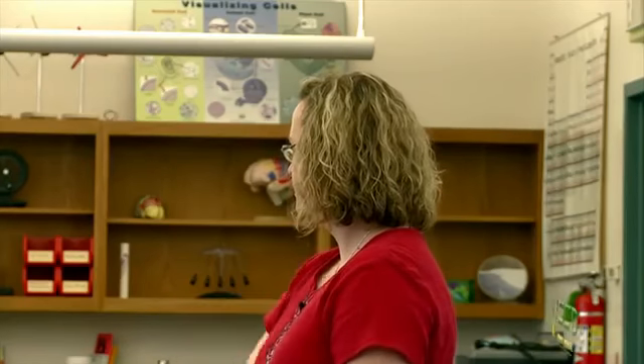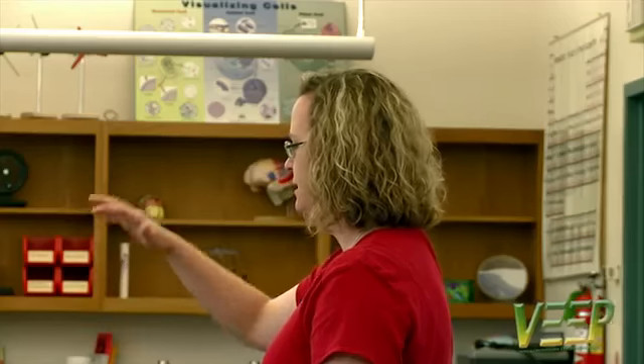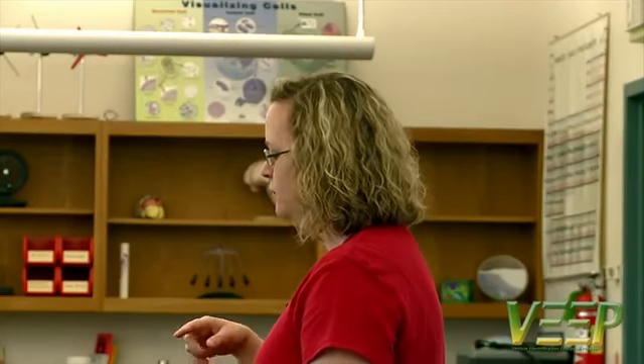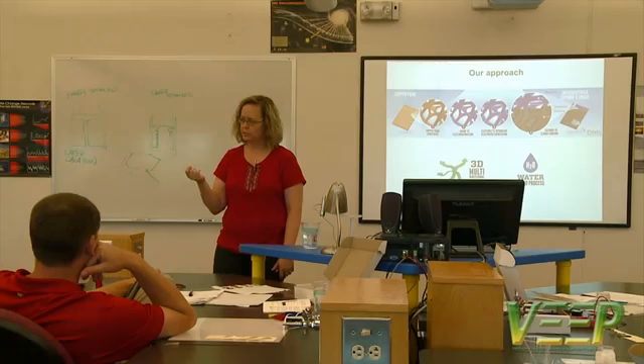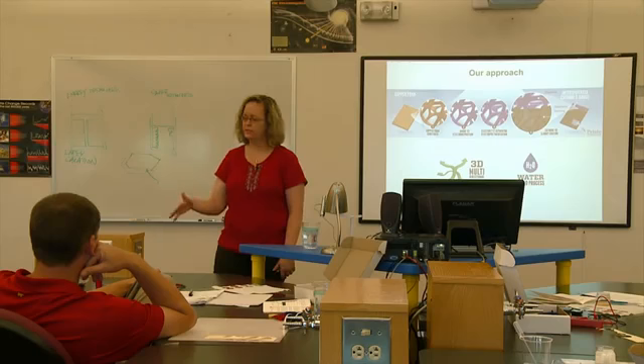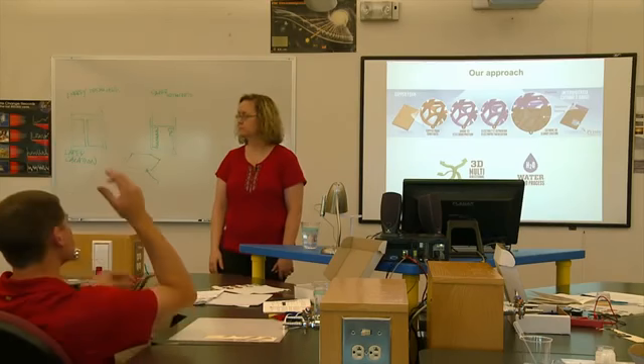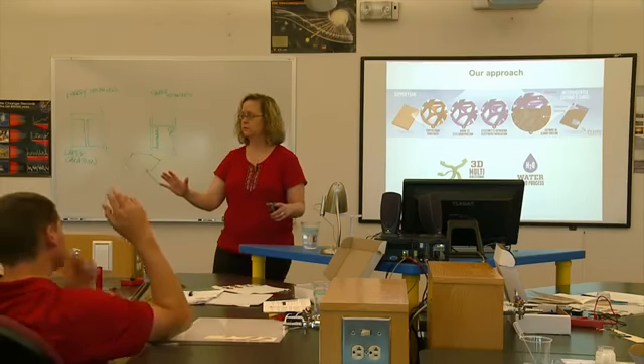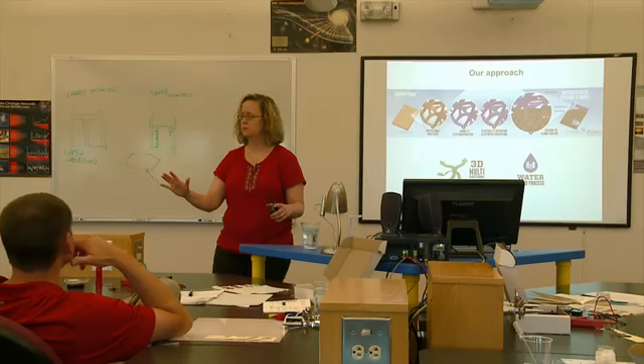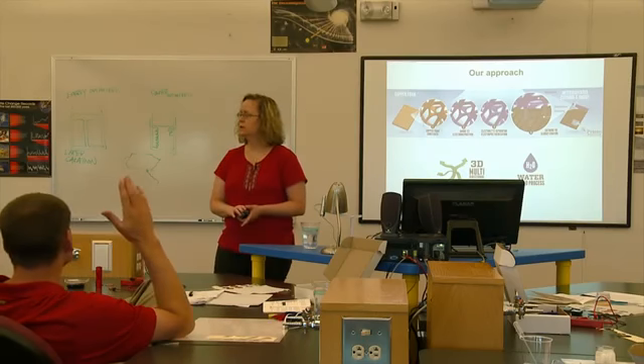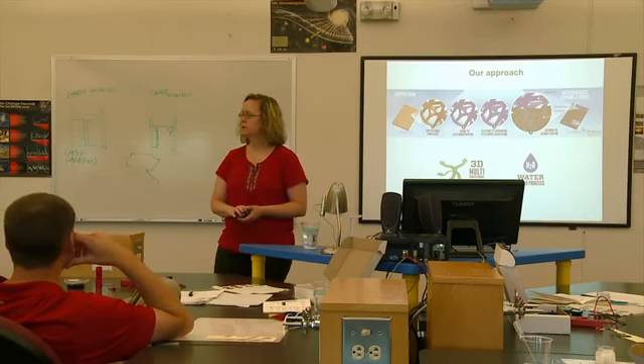The purple stuff I'm showing you, it takes us 60 seconds to plate. Take it out, put it in another rinse tank, put it in a polymer tank. That one I'll show you, that's a little trickier. We coat it, then we do a quick test to make sure it's perfect. If it's not perfect, we do a second coating. Then it goes in another rinse tank, and then it gets dried. So you can recycle your material, you don't have to reject it. That's right. In semiconductor, you don't. I mean, you get one shot.